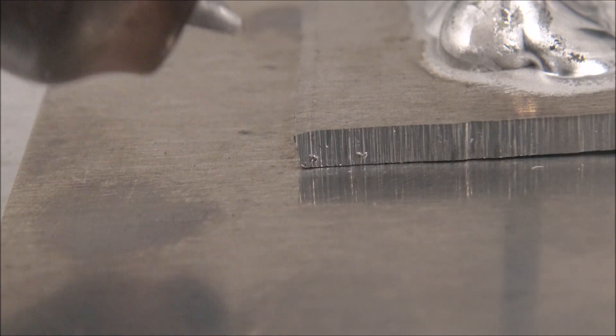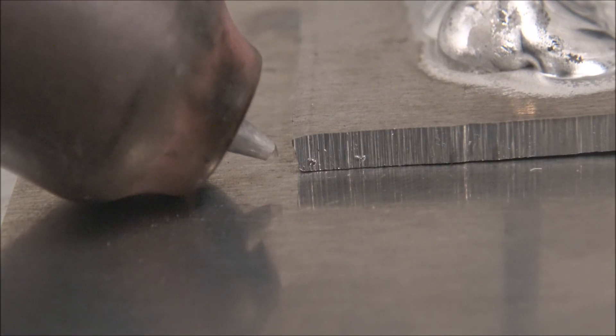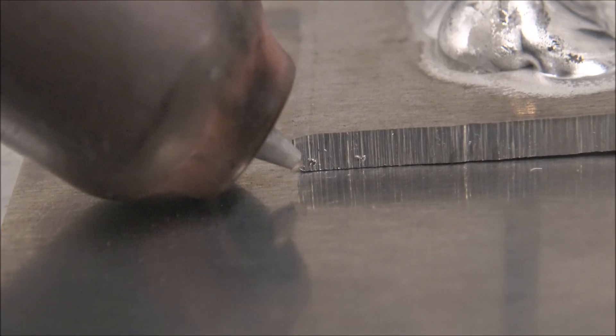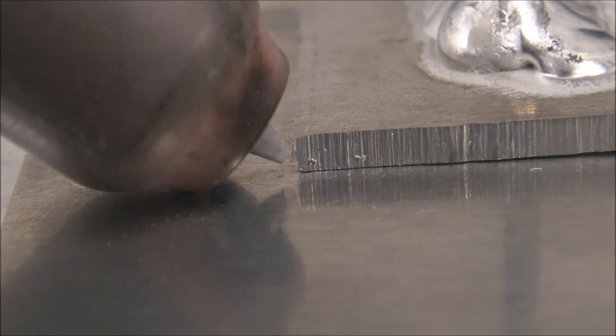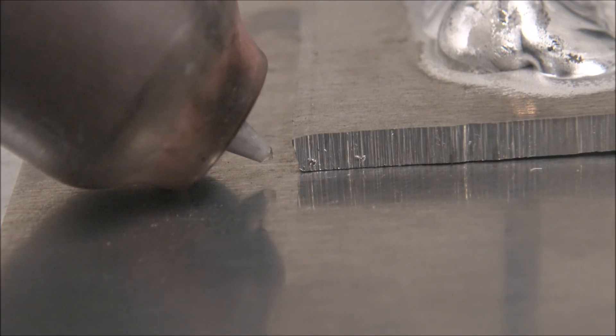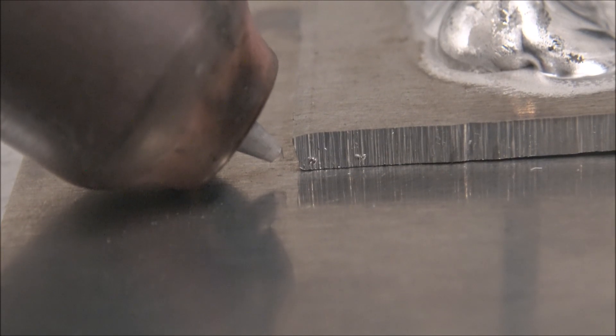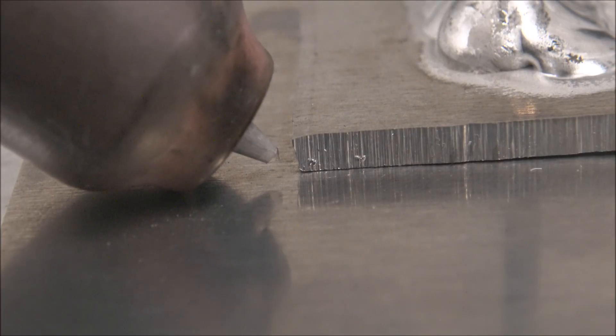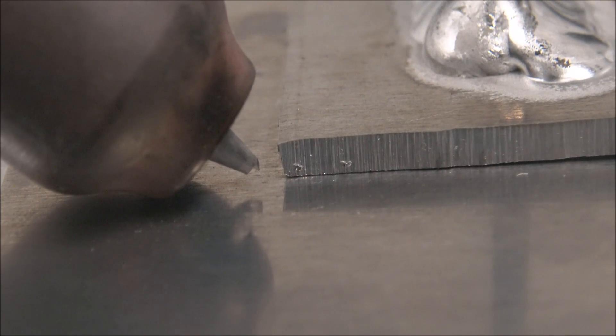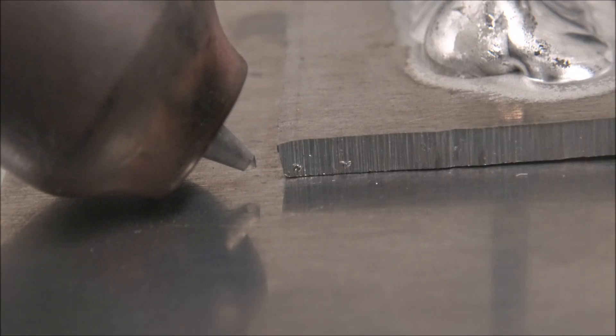This type of tack weld, I'll rest my cup down. Get this point dead center in that little corner. As close as I can without touching. But then you've got to be mindful this top part is going to burn back away. So I point down just a little bit to focus the heat on the base plate.